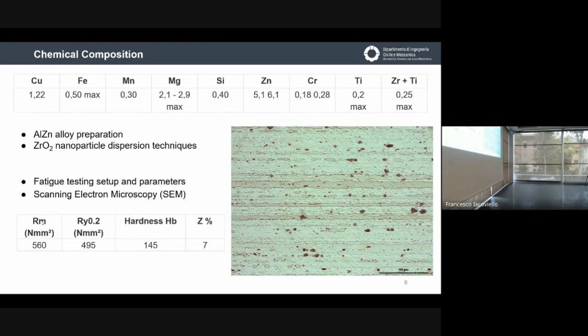So we try to change the treatment. Well, okay, I need some particles precipitated in the microstructure to block the movement of the dislocation. I can substitute the precipitate using nanoparticles: zirconium dioxide nanoparticles put directly in the melt without any heat treatment. After, if you can do other things, you can perform them.